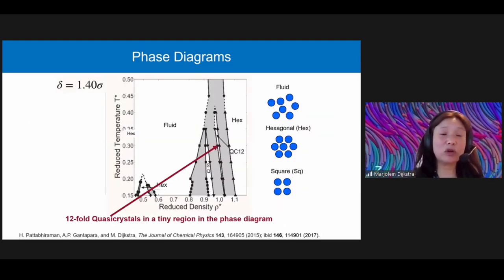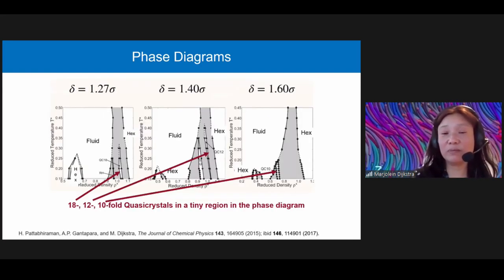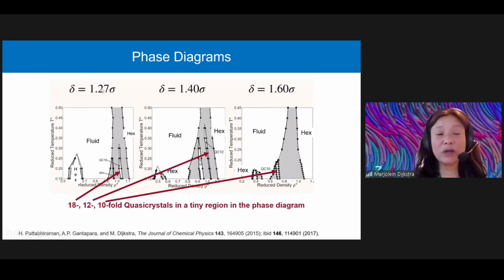The phase diagrams were already reported for this system. This is the phase diagram for a shoulder width of 1.4 sigma. In the temperature density plane, there's a low density hexagonal phase, a high density hexagonal phase, a square phase, and a fluid phase. And in a very, very tiny density regime, there's a dodecagonal quasi-crystal. It would be extremely cool if we can really inverse design and probe this very narrow density regime where this quasi-crystal is stable. We can also change the shoulder width. We can also stabilize an 18-fold and a 10-fold quasi-crystal, but all of them are stable in a very, very tiny region in the phase diagram.